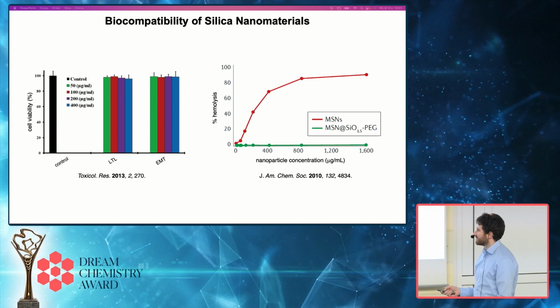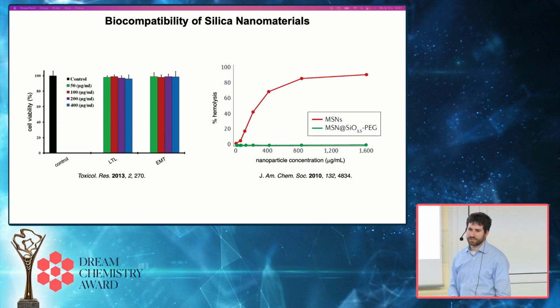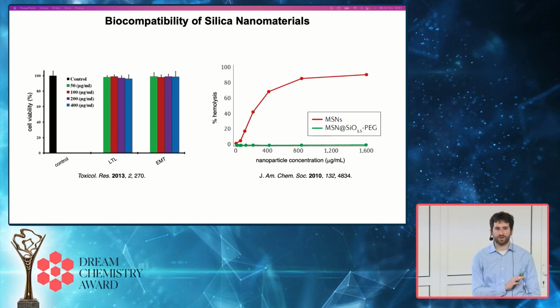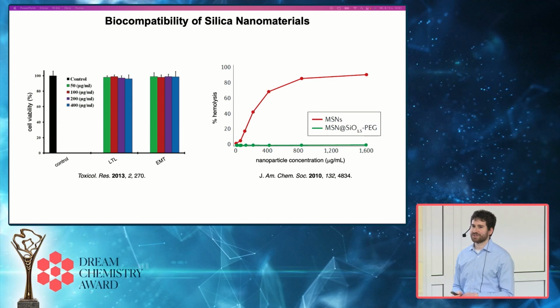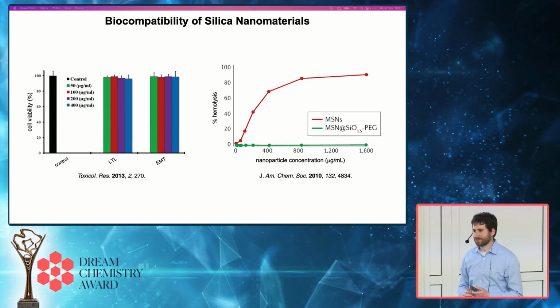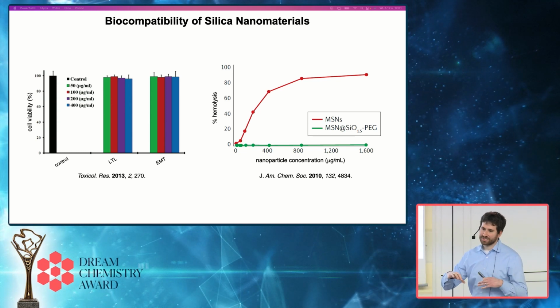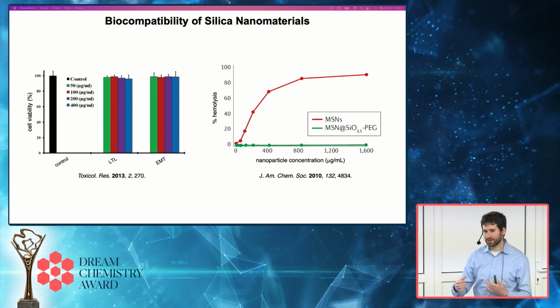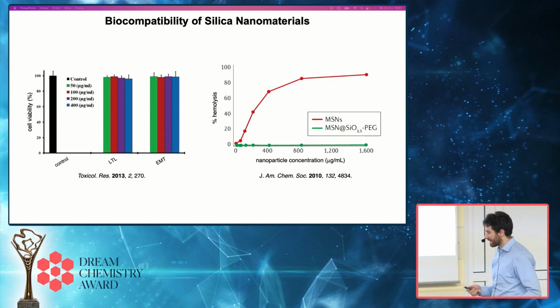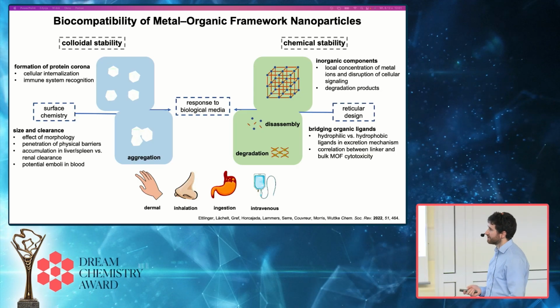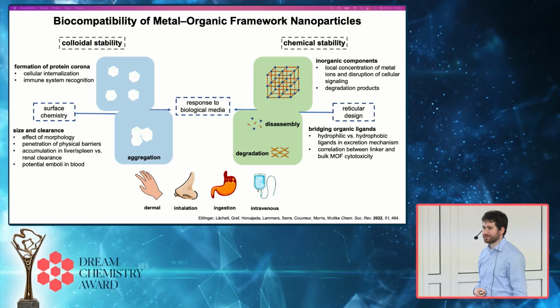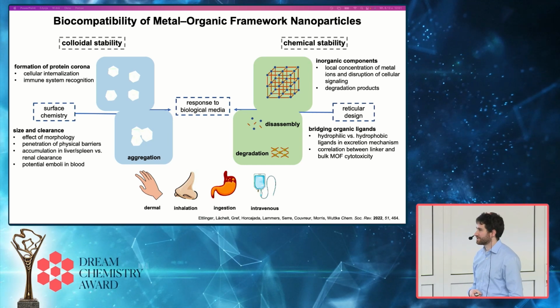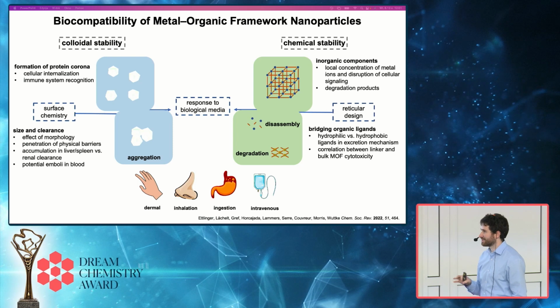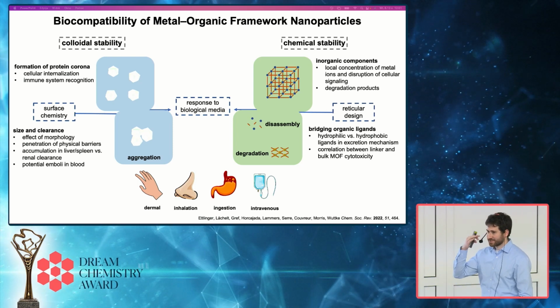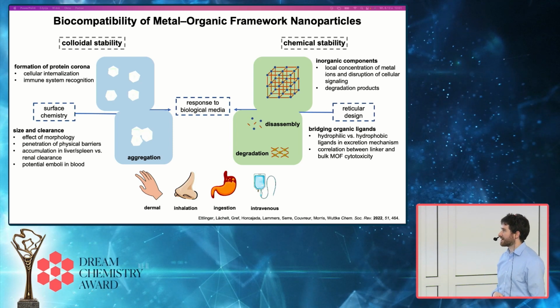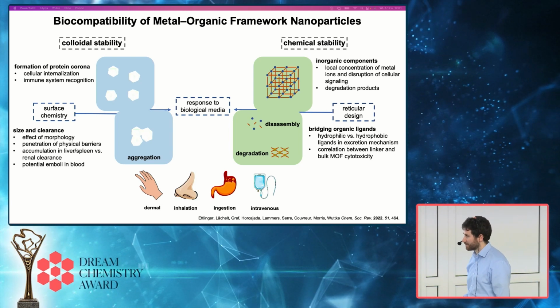But if you covalently functionalize the external surface with PEG, you can significantly enhance their biocompatibility and basically remove all of this hemolysis. And so this is just a demonstration of the fact that what's on the external surface of the particle generally governs its biocompatibility. What's on the internal surface for us is what governs its gas absorption and release behavior. And so we can independently manipulate these different aspects of particles. Similarly, for metal organic frameworks, there's a lot that's not really understood about their biocompatibility and their behavior in biological environments. A lot of this comes down to the specific metal organic framework, the size of the particles, what's on its external surface, and how exactly it's being administered and what it's interacting with. And so there's a lot to understand here that we're working on.